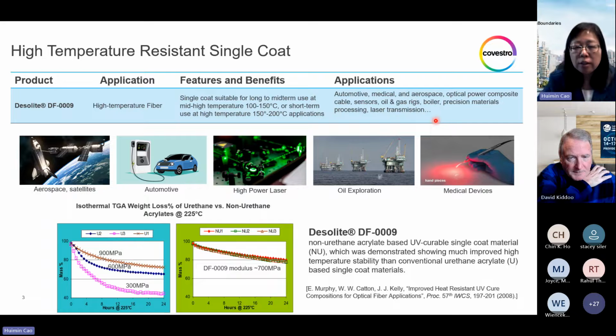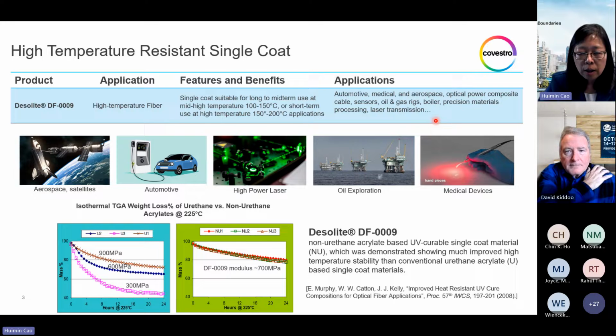The fluid resistance of this high temperature coating, we expect it should be even better than traditional coating. But the traditional urethane acrylate-based coating already provided very good chemical resistance towards typical chemical environment, whether in the cable or the gel immersion type of test. And this new HT high temperature coating should be even better because the primary coating is now designed at a slightly higher cross-link density.